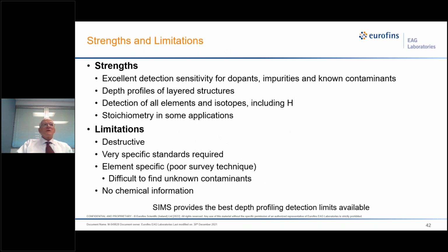So strengths: excellent detection of dopants and impurities, depth profiles of layered structures, detection of all elements and isotopes, including hydrogen, stoichiometry in some applications. Limitations: it's destructive. We do put a hole in the sample. Very specific standards are required. That's a huge limitation. Element specific, it's a poor survey technique. If you don't know what's on the sample or in the sample, it's best to try to use something else.